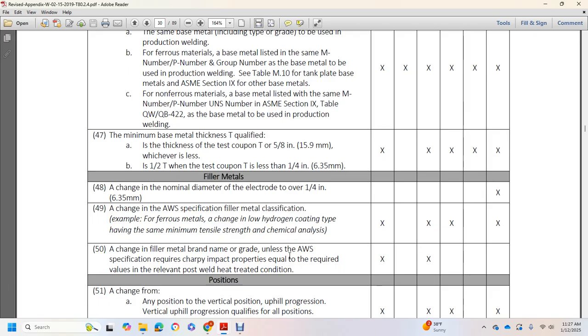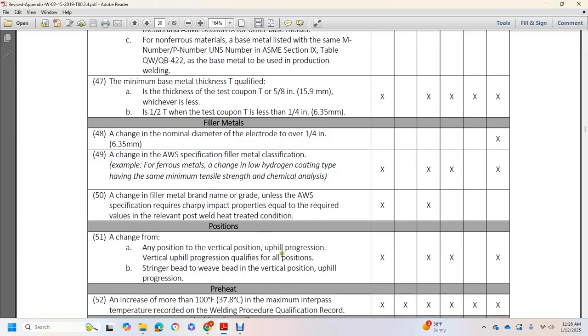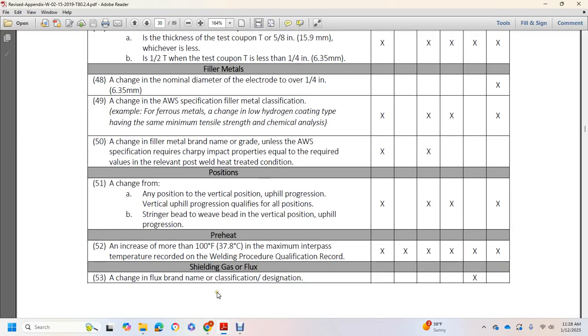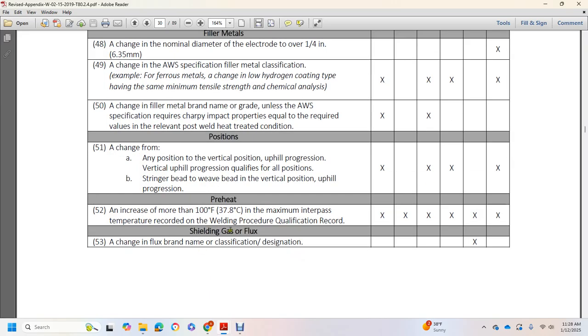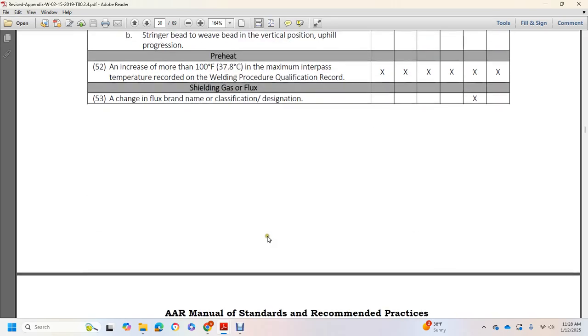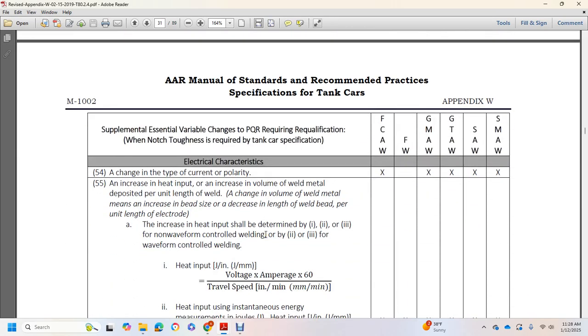Change in the AWS specification filler metal classification. For example, ferrous metal changes of low hydrogen coating type have the same minimum tensile strength and chemical analysis. Change in filler metal grade, brand name or grade, unless the AWS specification requires Charpy impact properties equal to the required value for the relevant post-weld heat-treated condition. Position: change from any position, vertical position, uphill progression, vertical uphill progression qualifies for all positions. String bead to weave bead with the vertical position, uphill progression. Preheat: an increase of more than 100 degrees Fahrenheit in the maximum interpass temperature recorded in the welding procedure qualification record. Shielding gas or flux: any change of flux brand with a classification designation. Change in the type of current or polarity.